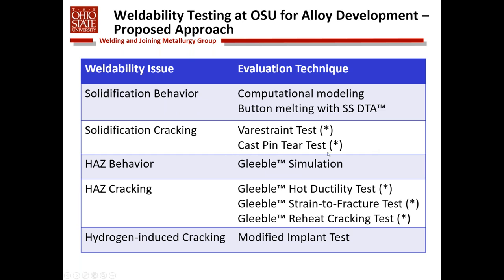We have basically redeveloped this test for our own purposes. When we look at heat affected zone behavior, most of the testing that we do at OSU in terms of quantification of weldability involves the Gleeble. So the original Gleeble was developed really to study heat affected zone behavior in materials, in stainless steels and structural steels back in the 50s and 60s. But we can also use it very effectively to look at heat affected zone cracking phenomena.